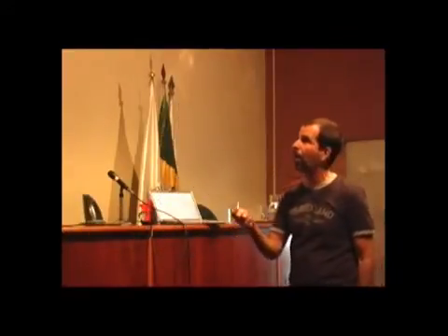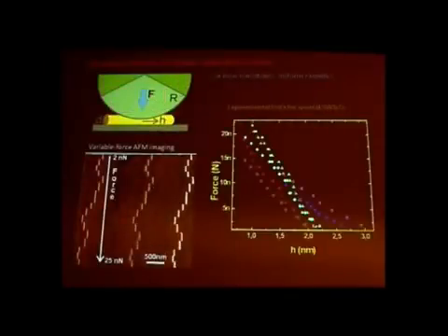This transition is reversible. When we were doing that study, we asked ourselves, well, how does the nanotube deform? Then we did the experiment of pressing the nanotubes with the AFM tip, and here's the experimental result. As the force increases, the height of the nanotube decreases as should be expected, but each nanotube deforms in a different way.